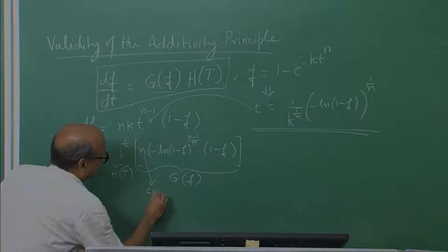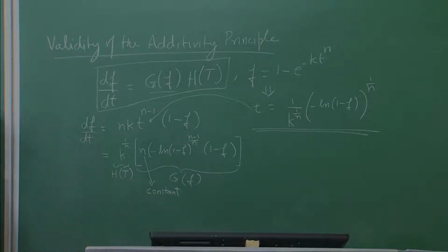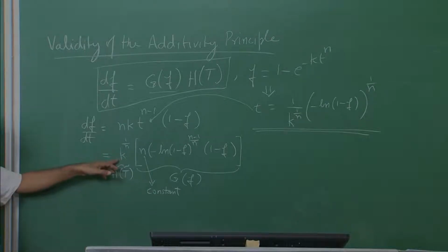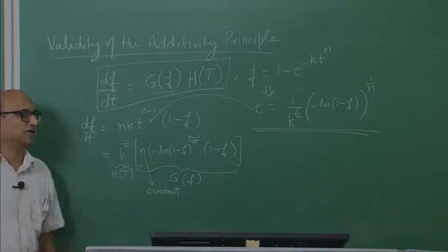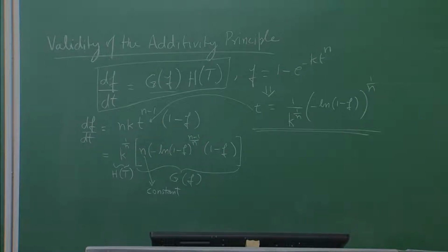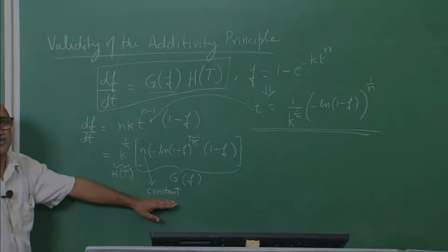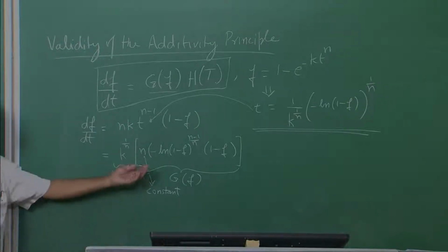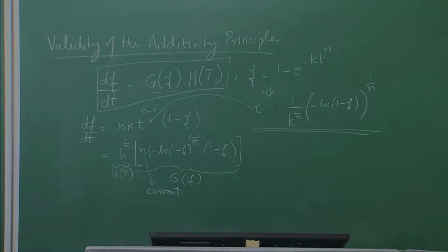So, n is independent of temperature, and only k is a quantity that varies with temperature. All those Avrami curves that I had shown for different temperatures could result if k is a function of temperature while n is a constant. Now, is this really true? Well, in many systems this could actually be approximately true, in the sense that n represents a mechanism of the transformation.